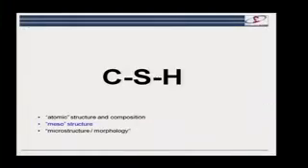This part, the atomistic structure, I think is now pretty well established, with a pretty high level of agreement. This next part, the mesostructure, is probably the area in which there's most controversy and most uncertainty about CSH structure. And unfortunately, this is exactly the level that is important for this whole area of water transport. So questions you would think would be very simple, like how much water is there in the CSH structure at a given relative humidity, we don't know well because of this uncertainty about the mesostructure.